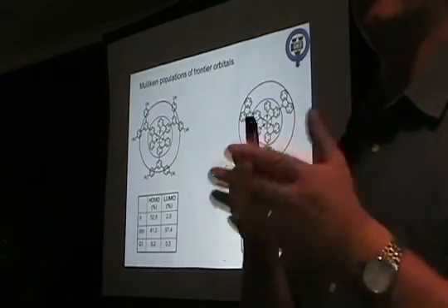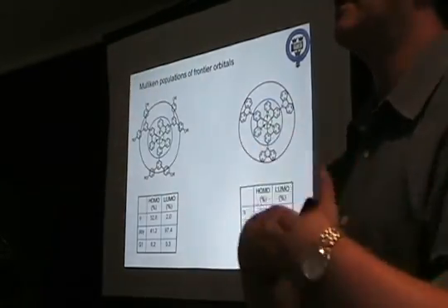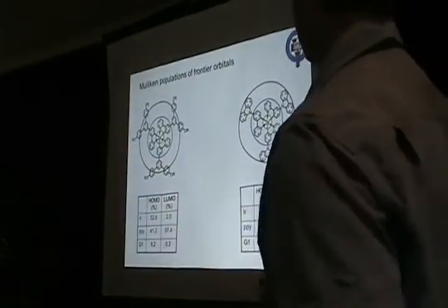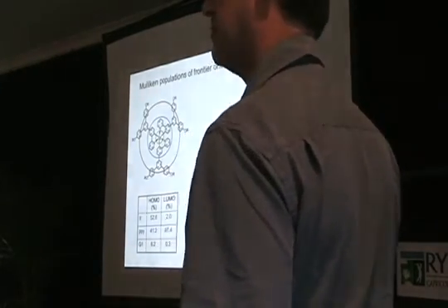And so that, again, fits with this whole hopping mechanism that we saw earlier, and going from the first generation to the second generation, the charge mobility decreased. As soon as we put the carbazole on, though, the picture changes completely. What we now have is the same sort of target diagram, but now we actually have 40% of the HOMO density sitting on the carbazole units.